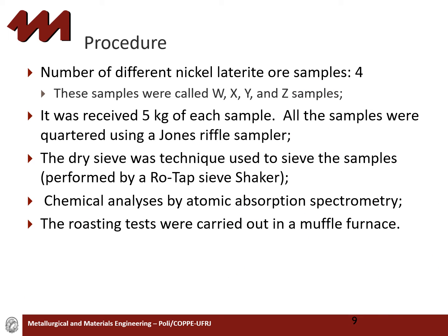Four different samples of nickel laterite ores from different regions of Brazil were investigated. The samples were denominated limonite W, red limonite X, limonite rich in chalcedony Y, and limonite Z. We received 5 kilograms of each sample. All the samples were quartered using a Jones riffle sampler. Dry sieving was the technique used to sieve the samples. It was performed by a Rotap sieve shaker. The chemical analyses were done by atomic absorption, and the roasting tests were carried out in a muffle furnace.